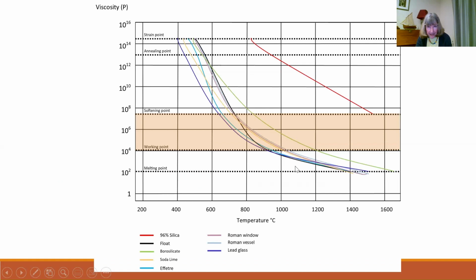So here we have, each line is a different type of glass calculated from the chemical content that's published of these different glasses. And it shows they are quite different. But if I follow the line of the 2 Roman glasses, they are there happily in the middle of all the other types of glass. This one over here is lead glass, which means it starts getting very soft at the lowest temperature. This green is Pyrex or borosilicate, and look, you need a very hot flame because it doesn't start melting until it gets to over 800. So that's a very, very high temperature glass. But there, happily in the middle, falls the Roman glass.